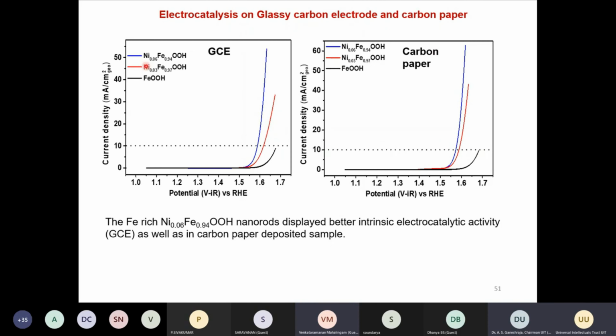We have compared the glassy carbon as well as the carbon paper activity for all these materials, comparing only iron oxyhydroxide with 3% nickel as well as 6% nickel. The 6% nickel shows a better catalytic activity, that means lower overpotential, compared to the other two samples. Whereas iron oxyhydroxide, you can see, doesn't reach even 10 milliampere per centimeter square. Similarly for carbon paper, of course the value is slightly better. And you can see that both the 3% and 6% nickel samples show better activity compared to the only iron oxyhydroxide samples.